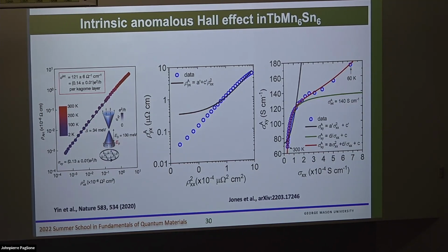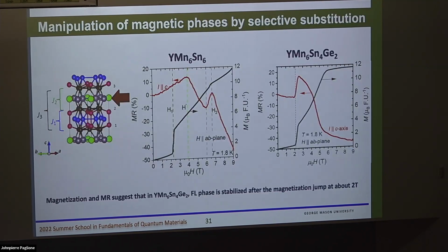So one thing that we learned from this is that we have to be really careful. The idea in the Kagome system was coming from a two-dimensional system, right? Now here we have a three-dimensional system, and it's already a ferromagnetic system. So for ferromagnets, whether they are Kagome or whether they have Dirac or not, you expect to get some sort of anomalous contribution because the bands split. So this seems like it's coming from other bands mostly, and probably not from the K and K prime contribution. That's what we found.